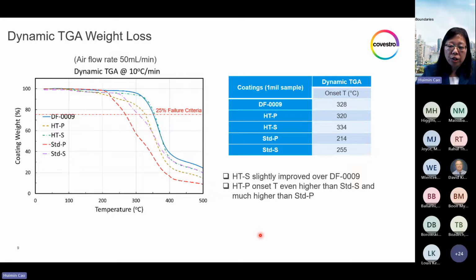And here is a dynamic TGA weight loss comparison of these coatings, which is a quick way of ranking the thermal stability of different materials. The onset temperature, or oxidation induction temperature, OIT, is an important parameter to rank thermal stability. As you can see, the HTP has only a slightly lower onset temperature than the single coat, and it is way higher than a standard primary. And HTS, of course, is even slightly higher than the single coat and way higher than the standard secondary coating.